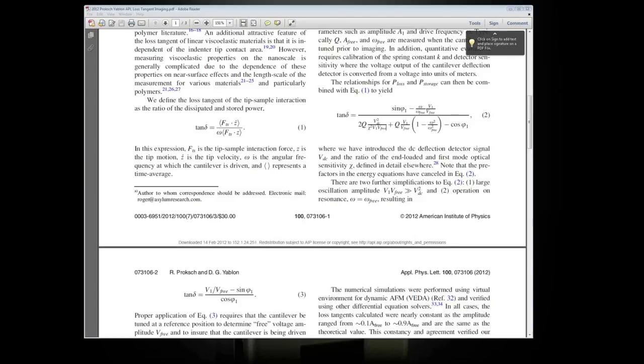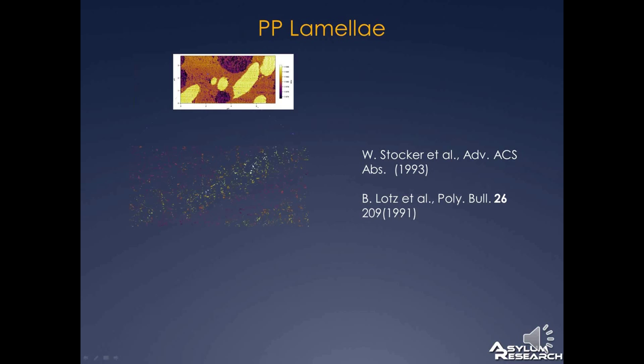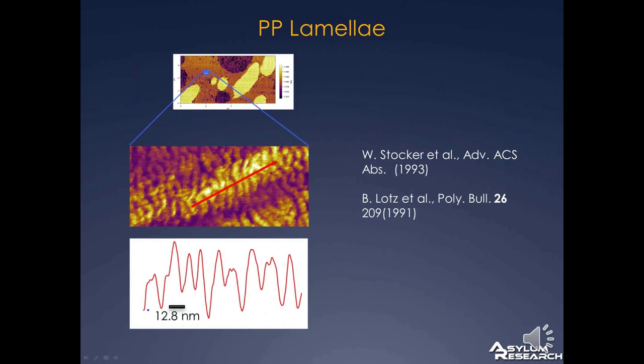What we do see frequently is that in the second mode, the quality factor doesn't grow as high, but the resonant frequency goes up. So the response time in the second mode is much faster. So time and again, we see much more spatial resolution in the second mode than we do in the first. What we haven't done right now is see if when we turn on the FM loop, it becomes even faster. Maybe so. Right now, experimentally, that hasn't been proven.